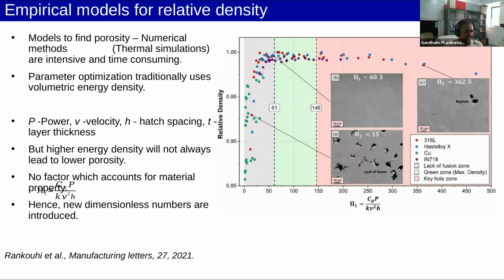Now, here is a very nice paper, which I like very much. It is also very recent, from this year itself. They have discovered a nice non-dimensional number using which you can predict the density you will get, that is, how much porosity you can eliminate. So without having to go into the details of the microstructural formation, you can predict empirically what kind of density you can get. Now we have verified this and found that this is a very good measure.